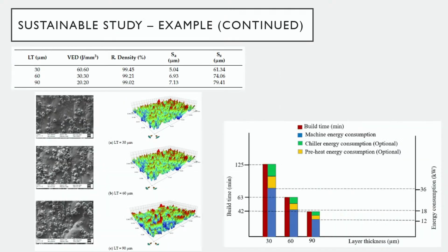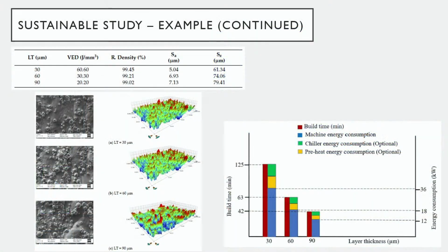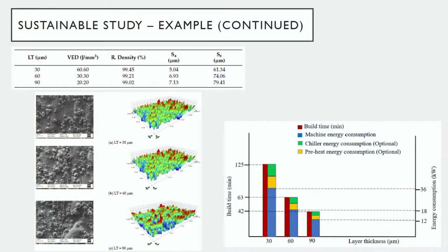In terms of the surface, usually we have very high surface roughness. I will come to the reason why is that. Like when we mill or lathe machine, you expect the surface roughness is in the range of 3 or 5 microns. But here very often we go a bit more than 25 microns surface roughness. And if it's EB, not laser, it's more than 50 or 70. So definitely you need post-processing to enhance the surface profile and surface quality. So I got the 90 microns with that surface roughness.